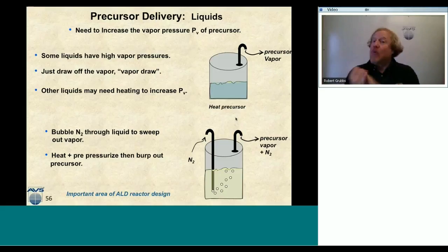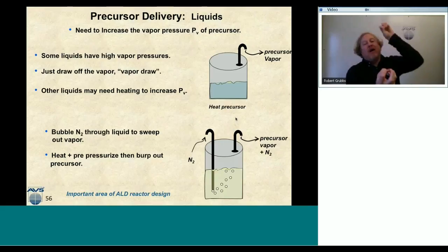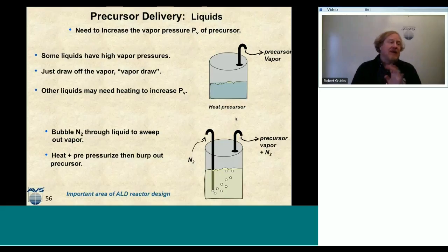So some liquids, like I mentioned, water or trimethyl aluminum, have high enough vapor pressures where we can just sit there and draw off the vapor. The vapor pressure of water was like 20 torr, I think. The vapor pressure of TMA was like 10 torr. That's plenty of vapor to just draw off the top, because as soon as we pull that off, it's going to give us a constant draw of 10 torr, 20 torr of vapor. Now, other liquids, we can actually heat the precursor to get the vapor pressure up. We can do that with liquids, just heat them up and we get substantial vapor pressure.